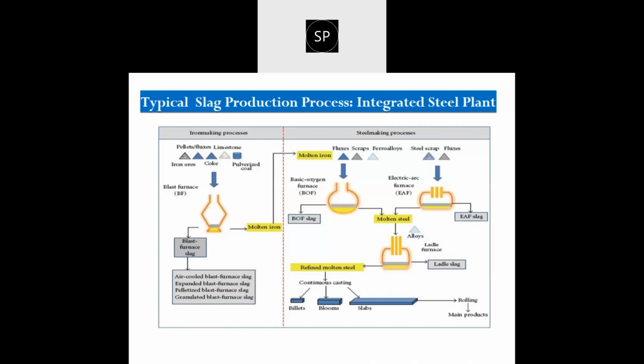If the blast furnace slag is air cooled, then it can become a source material as a substitute of natural aggregate in road construction. And if it is granulated with the help of a water quenching process, then it gets converted into granulated blast furnace slag, and this type of slag can be directly utilized for the production of Portland slag cement, PSC. As per the advent of the new IRC code, 30% replacement of OPC has been permitted by using ground granulated blast furnace slag in pavement quality concrete, so PQC.